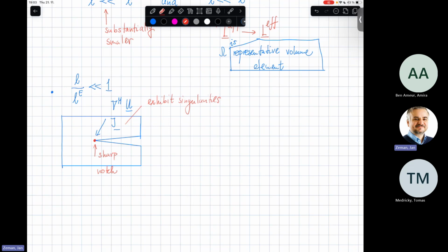The second one is that, for instance, if you are in a really close vicinity of this boundary, then again, there is something which is called boundary layer. And boundary layer corresponds to the fact that there is a very, very concentrated vicinity of the boundary in which your solution changes substantially. So again, in these regions close to the boundary, using this homogenized coefficient may be questionable because you do not have this setup, right?